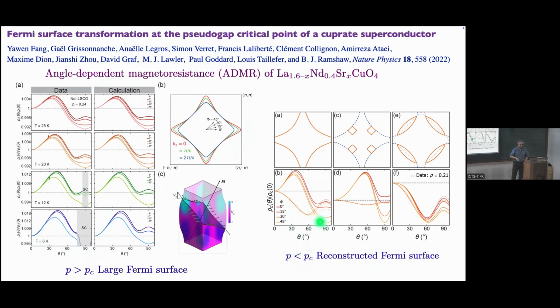The data is here, and I think the dashed lines are the different theoretical models. The large Fermi surface simply doesn't work. Neither do these electron pockets, which are present at very low temperatures when there's charge density wave order. But what does seem to work are these hole pockets, which have not just the front side, but also what's called the back side.